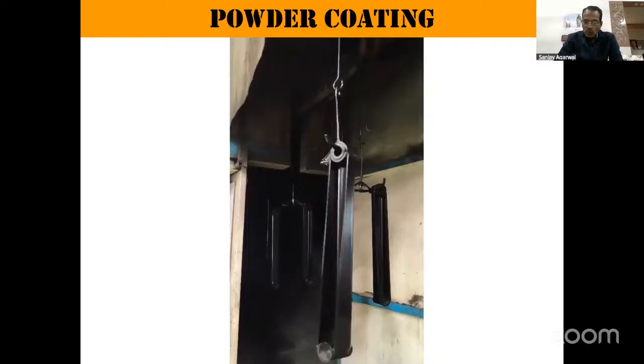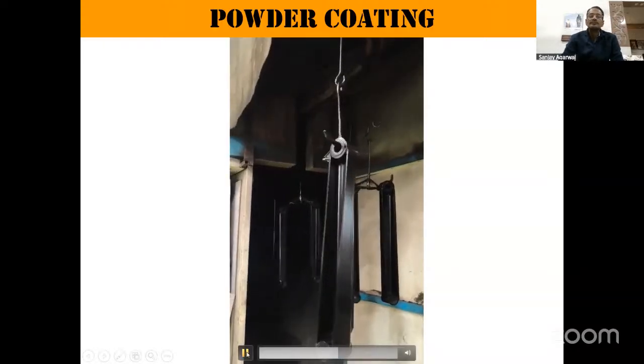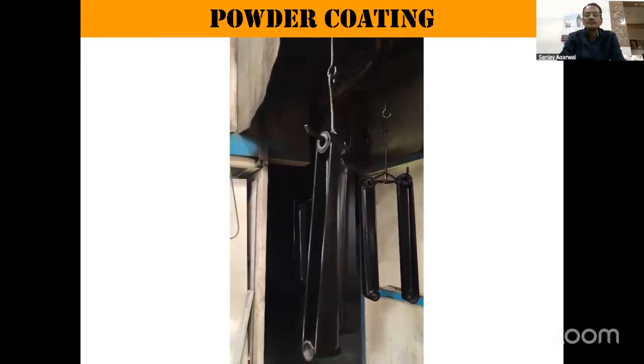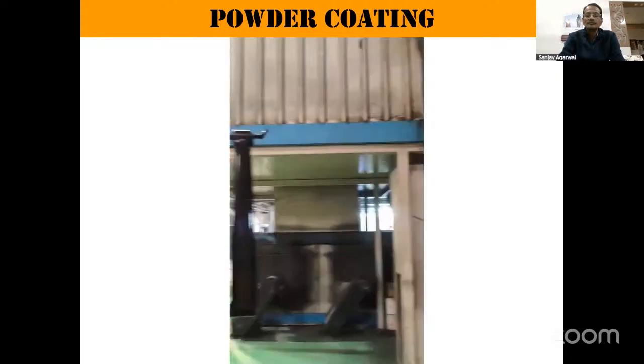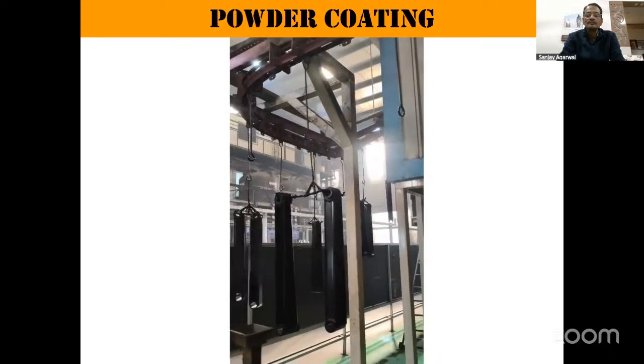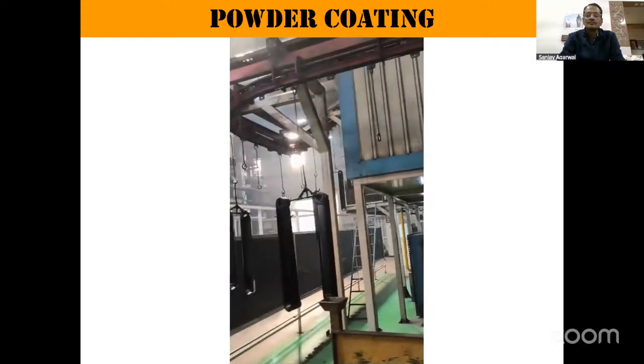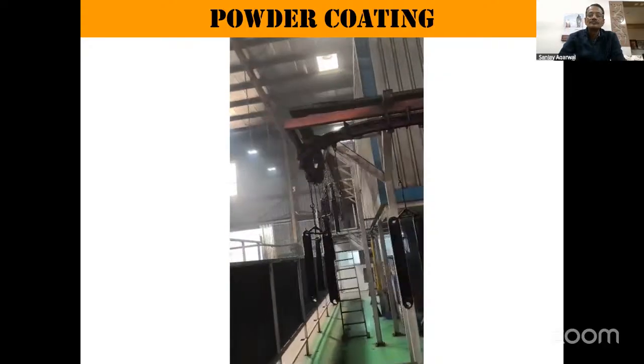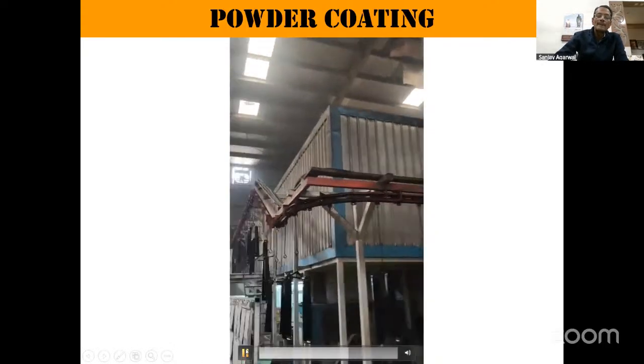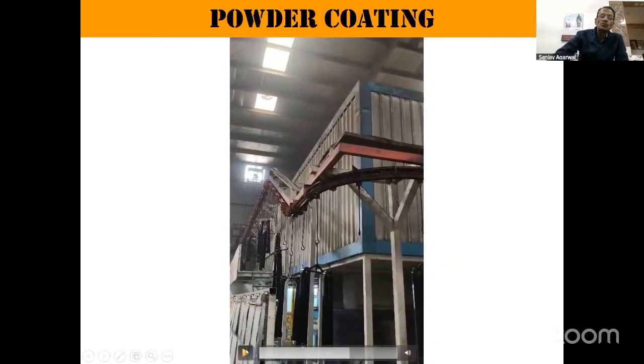Parts are going to the curing oven and then coming out, and the paint is baked now. Parts should stay inside the oven for 30 to 40 minutes, and the conveyor speed is set according to the length of the baking oven. The part is moving on the conveyor. It is a cooling time for the parts.